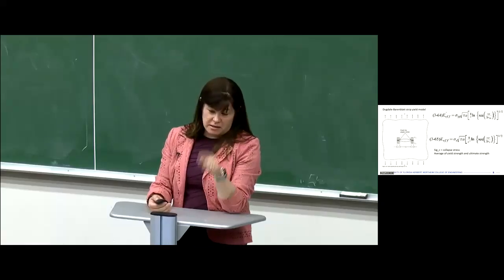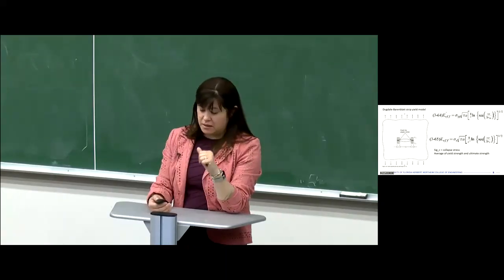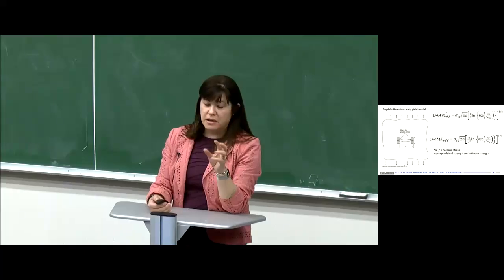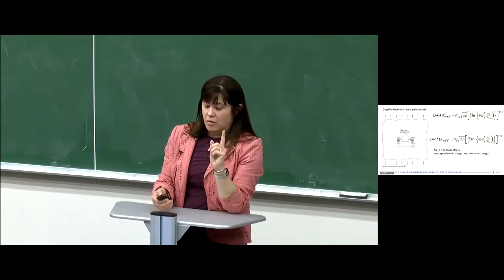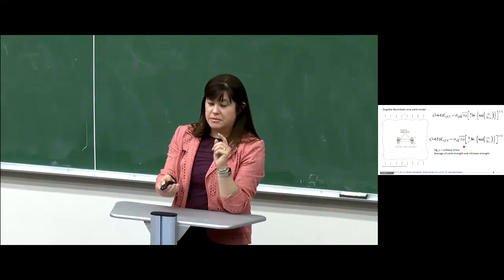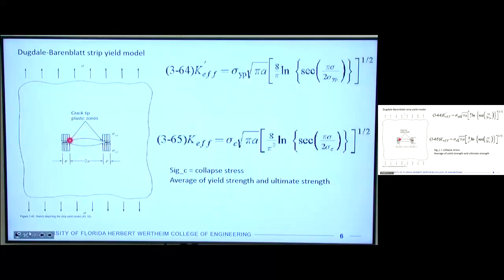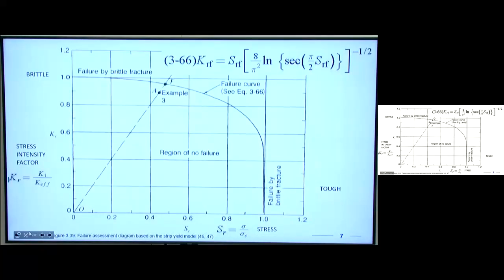if I'm assuming this allows me to get an effective fracture toughness, I'm going to put together a map that tells me, am I going to have a plastic collapse, right, this sigma C, if I do have a crack with plastic deformation on the edges, or am I going to get a crack that propagates? And so am I going to get basically a collapse of this entire region, or am I going to get a crack that propagates across? Because both of those could happen in this situation. And so they put together what's called a failure assessment diagram.